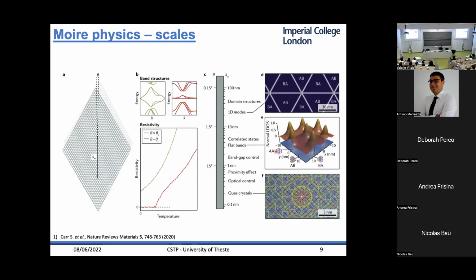Or if the angle is in this regime between 1.5 degrees and 5 degrees, let's say, we have almost, for all kinds of material, this phenomenon of band flattening, which I'll talk about more in detail later, and the correlation effects. And then if we keep on reducing the twist angle, then we have this nice domain structure that forms, where the system tends to enlarge the regions where the binding energy is more. So this is AB, for example, for graphene. And in between these AB regions, there are these very fine channels where all the strain is localized.